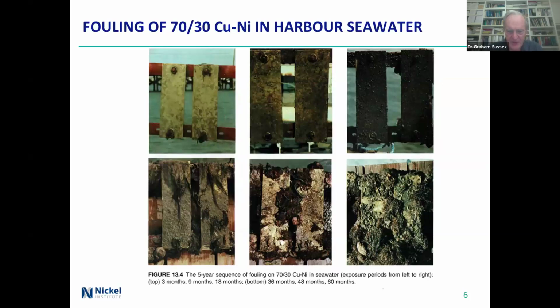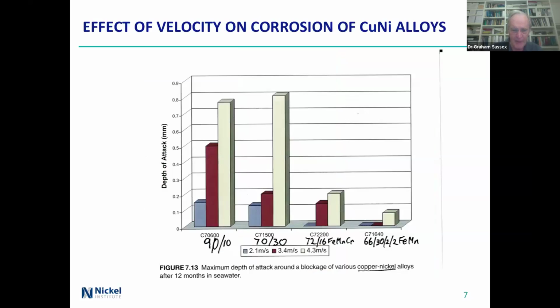This is the same thing for 70-30 copper nickel, so a bit less copper, a bit more nickel. The first one looks very much the same at 3 months, 9 months, 18 months across the top row, and they're reasonably the same. And then again, across the bottom, you start running out of protection. Basically, because it's sitting in a harbour, there's nothing actually doing anything. And if you get any slime sitting on it, then basically the copper stops dissolving and protecting.